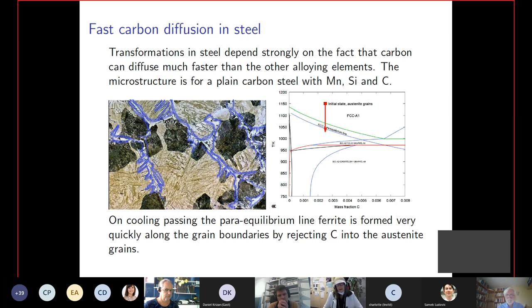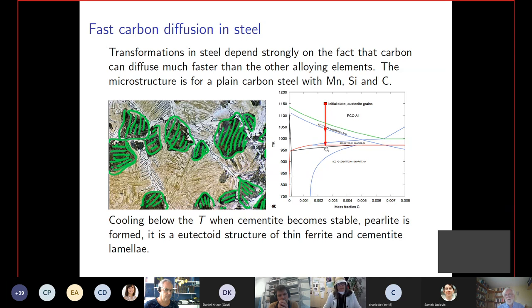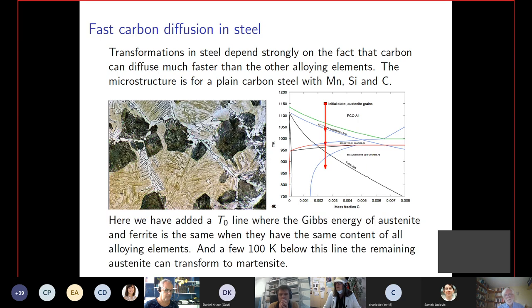It's easier to nucleate. Then you form pearlite when you come down to this temperature, because cementite is stable. And pearlite looks like a single phase here, but it's actually a lamellar structure with ferrite and cementite, which I tried to emphasize. Then at the end, if you cool fast enough, you can go below what is called a T0 line, where you have the same Gibbs energy for the ferrite and the austenite, independent of the composition. And then you can form martensite, which is the hard structure here. And that is what gives you a strong material. It's a bit too brittle by itself, but one can heat treat it a bit afterwards to make it a bit softer. And this structure is actually not very good, because you have cooled it a bit too slowly. Normally you want only martensite when you want to harden it.